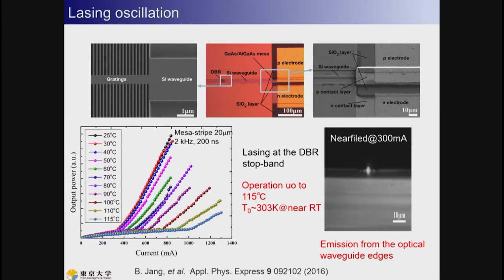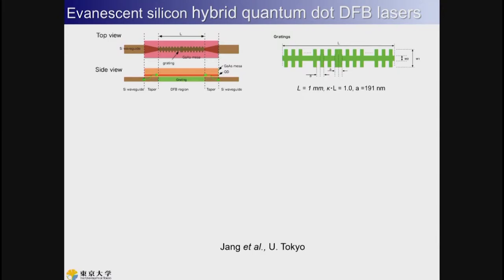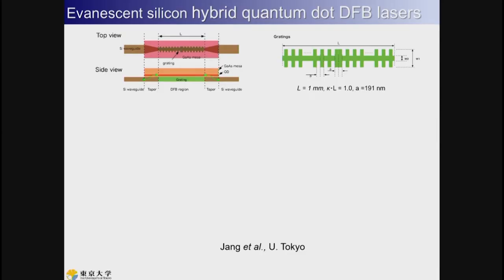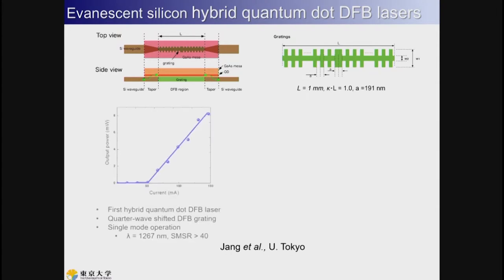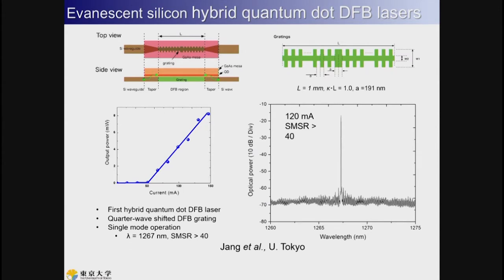Since we are using DBR structure, we still cannot define single mode operation. Therefore, instead of using two DBR mirrors, we processed the formation of the DFB structure in the silicon waveguide. In this case, single mode operation can be guaranteed if enough coupling is realized. Indeed, we achieved our first hybrid quantum dot DFB lasers, and the side mode suppression ratio is over 40, so single mode operation is realized.